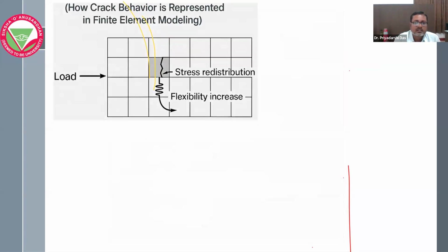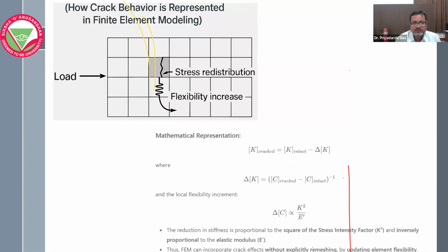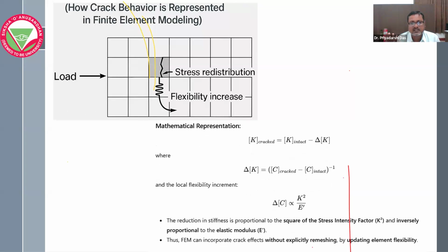So now the finite element modeling, where the mesh size is refined at the region where the crack has occurred, the stress redistribution will give the flexibility increase rate. From that flexibility increase, we get the reduced stiffness values. So mathematically, this can be presented as this. If K is the global stiffness of the structure, it is the stiffness matrix of the intact structure minus the stiffness matrix of the crack, and the local flexibility can be computed through this. So this formulation can be implemented through finite element modeling.